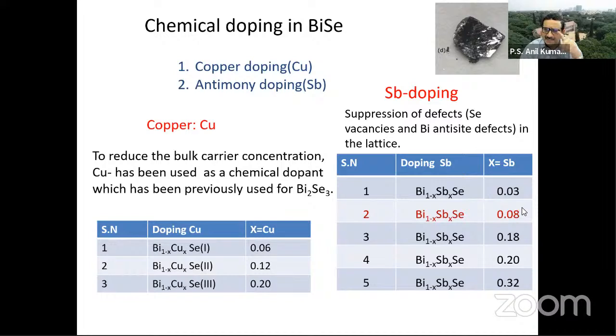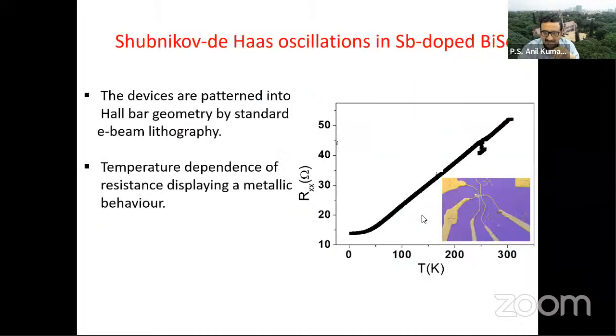In the remaining few minutes, I will show the results coming from 8% antimony doped bismuth selenide. Again, all these crystals take quite a long time, so we should appreciate the patience of the students. Each crystal takes around 15 days to grow. At the end of the 15th day, you realize whether you have to throw out this crystal or you can use it. So finally, after all these things, Kunchalada got a very good crystal, Bi(2-x)Sb(x)Se3 with 0.08 antimony.